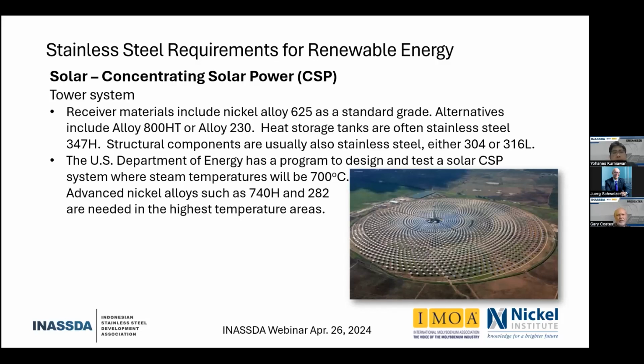Heat storage tanks for molten salt can be 347H, and they will typically use the structural stainless steels 304L, 316 as support structures. These are moving structures, so you want to be able to have high fatigue life in a somewhat corrosive environment. And right now, the U.S.